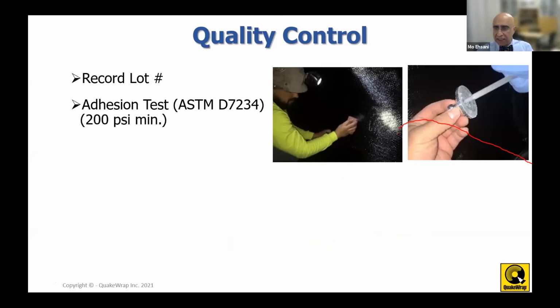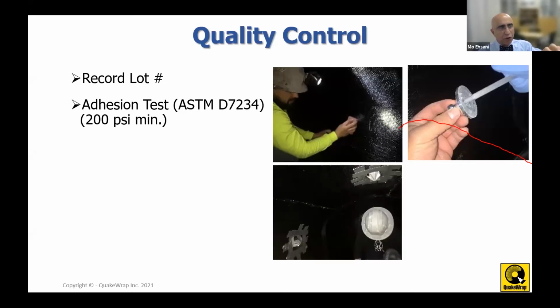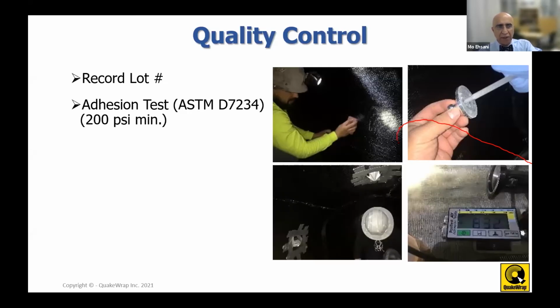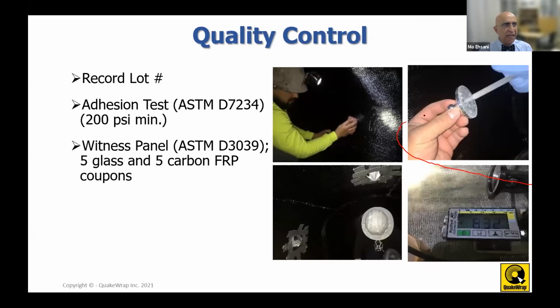The way this is done is you glue or bond these pucks to the surface of the structure, and then we core around this and pull it. Oftentimes we get a lot more than 200 PSI, but 200 PSI is the minimum requirement. We also make witness panels of these samples, just like in concrete where you take cylinders for testing. We make these flat panels and test them later in the laboratory for tensile strength.